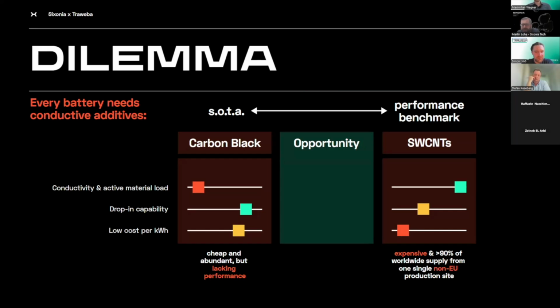So I guess you all know, if you're working in this field, that every battery needs conductive additives. And there is the state of the art, which is carbon black. And then there is a performance benchmark material that is used, which is single-walled carbon nanotubes. But the problem really is that carbon black is not so conductive, and you need quite high loadings to achieve a good conductivity in your electrodes. But it's cheap and it's abundant, but it's lacking performance.